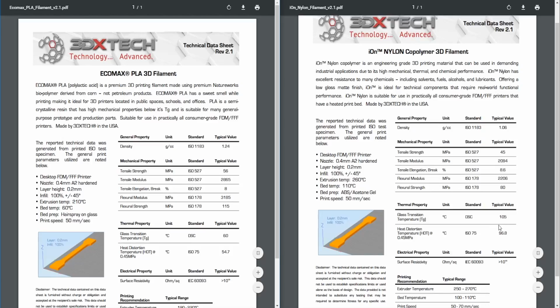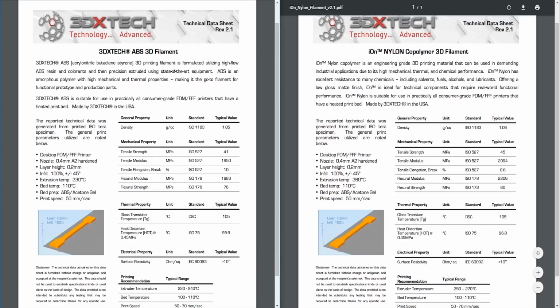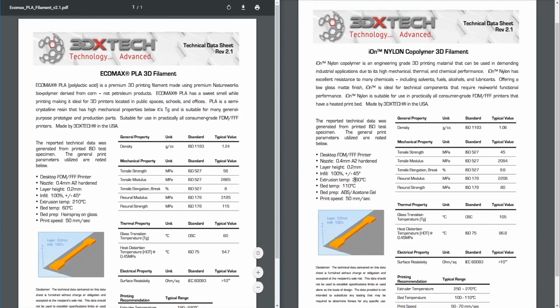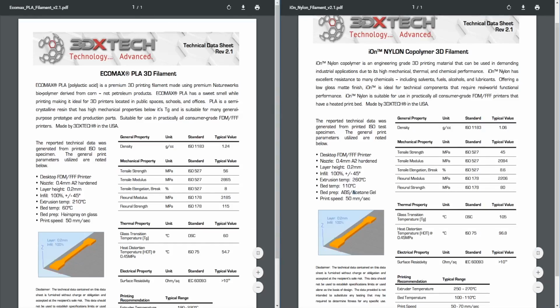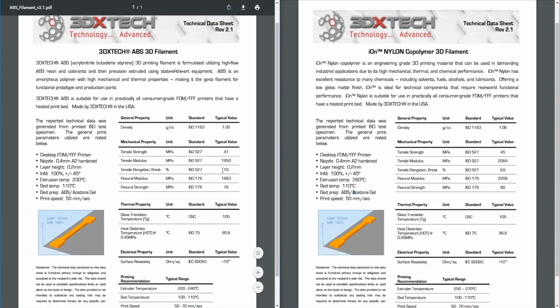Definitely about the same temperature stability as ABS, and from there you'd think you actually need to go another 30 degrees C higher to print. So a higher print temperature, 250 to 270 degrees, with the bed at 100 to 110. So it's a little bit harder to print than ABS. I think it's just another slightly stiffer version of ABS. So let's go ahead and check that out. Obviously PLA's got quite a bit of stuff on it.